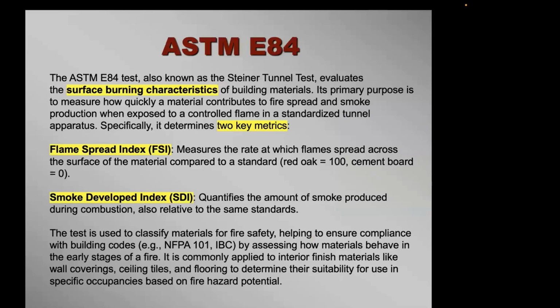The other argument I get a lot for FRPs is, oh, well, we're class 1 fire rating under ASTM 84. ASTM 84, known as the Steiner tunnel test or the tunnel burn test, is to evaluate surface burning characteristics of materials. It's not a fire rating test, it's a fire propagation test. So it's testing how fast that product burns. There are only two key metrics in ASTM E84: one is the flame spread index, and one is the smoke developed index.